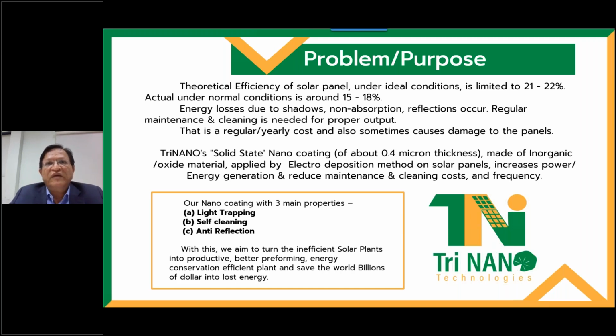And that regular cleaning, regular maintenance, is a recurring cost. So this is where we have tried to come in, for the inherent issue of the lower efficiency of the solar panel, and second, the need to clean and maintain the panels. So Tri-Nano Technologies have developed a solid state nano coating, which is about 0.4 micron thickness, made of inorganic ceramic oxide material and applied by electrodeposition. Each term I will explain later, but with this coating, we attain three main properties: light trapping, self-cleaning, and anti-reflection.